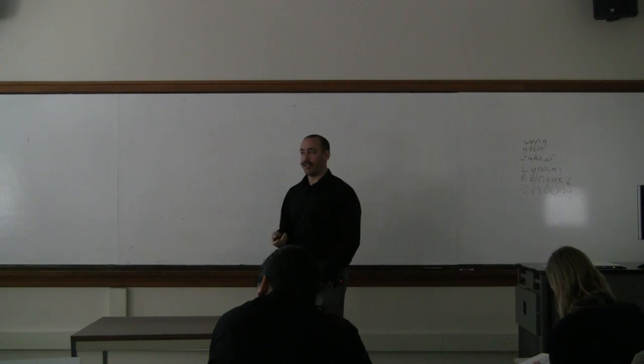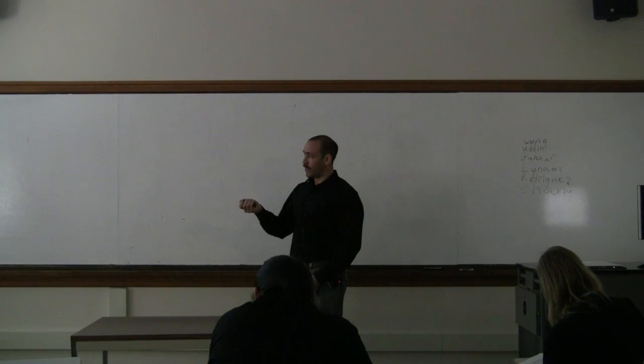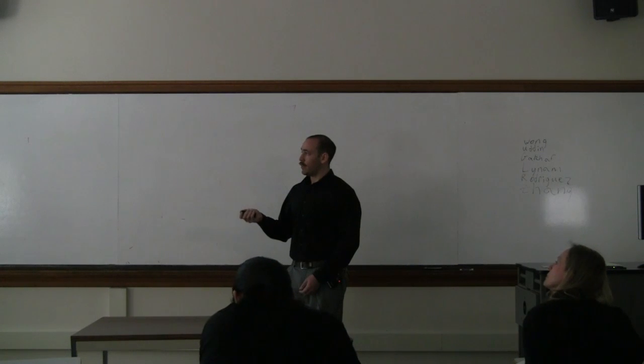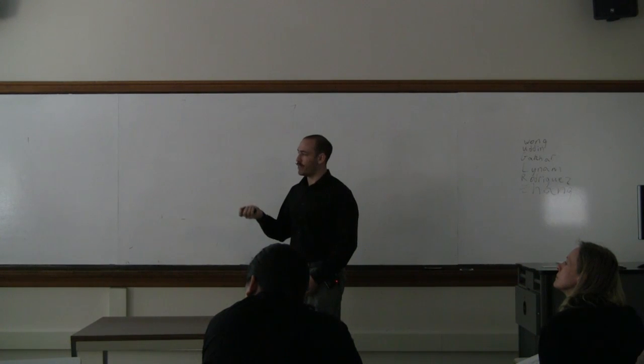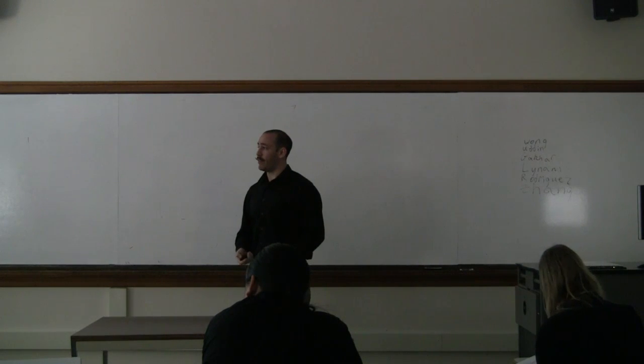Now this leads us to compare back to the original model shown for the chromate conversion coatings, where we have the different species present in 2 different layers. From there, when you compare the valencies, you have the chromium 3+ and the chromium 6+, and here you have molybdenum 4+ and molybdenum 6+. Now this leads us to believe that we will have the repassivation behavior. So how do we test this?